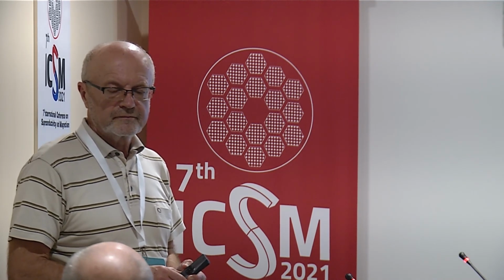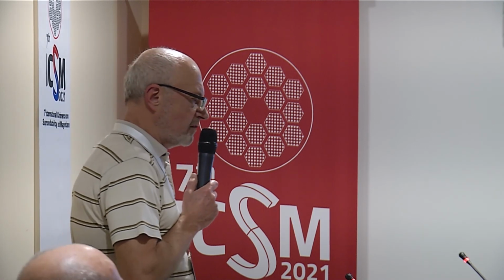Yes, please. Interesting phenomenon. The same question I had was already asked, so maybe a different one. The trick is point contact, because in the point contact you have a large electric field, a large gradient of that. Did you try to evaluate the size, some values of the electric field which you can achieve there? Yes, for several point contacts we evaluated the size, and the size is of the order of a few hundred nanometers, and the estimated lower value of electric field is 10 kilovolt per centimeter. And probably in general it should be larger, because in the case of a soft point contact we can have several point contacts. In this case, the electric field for a smaller point contact will be even larger.